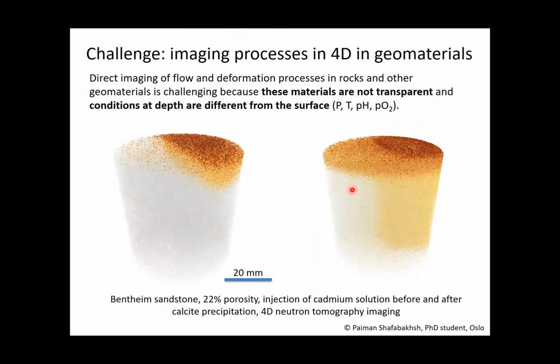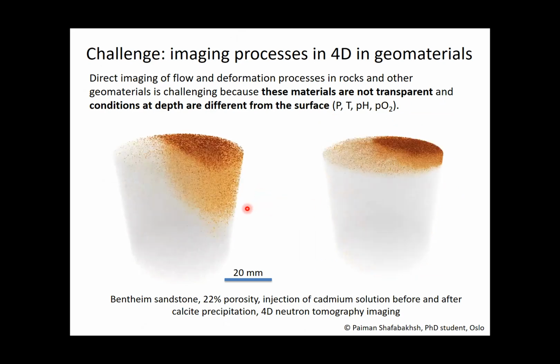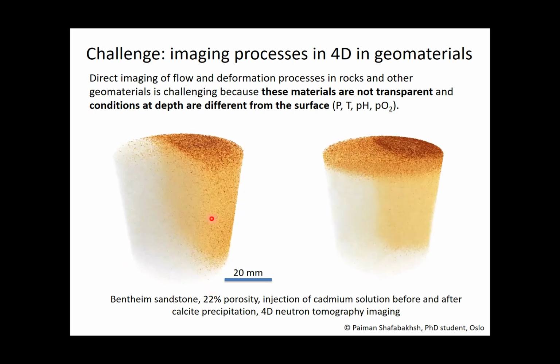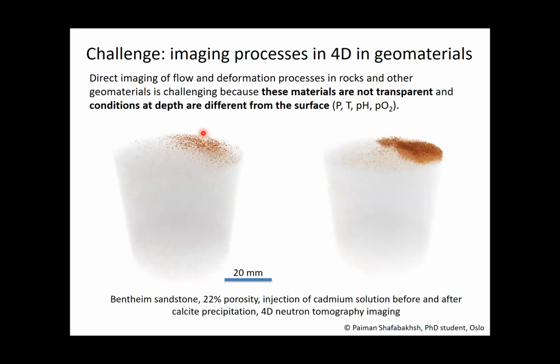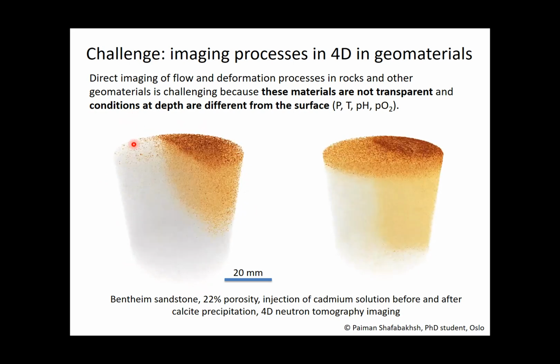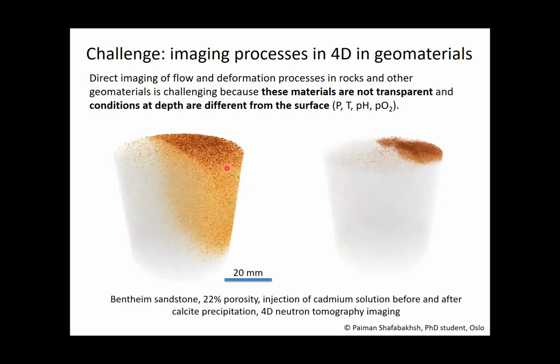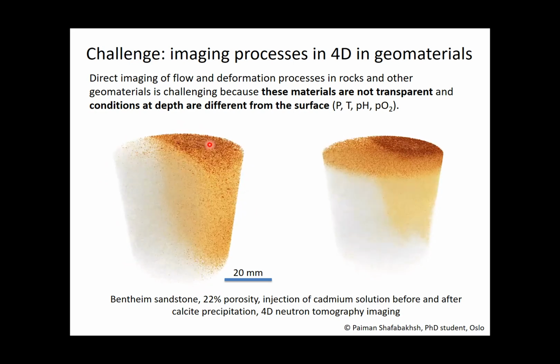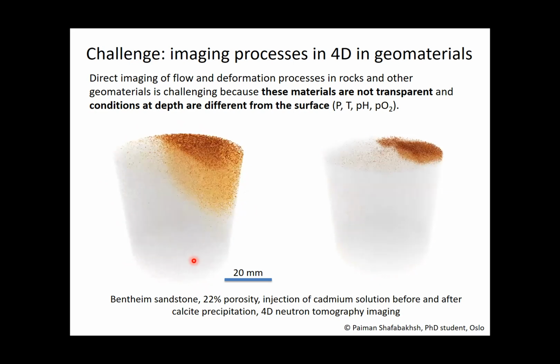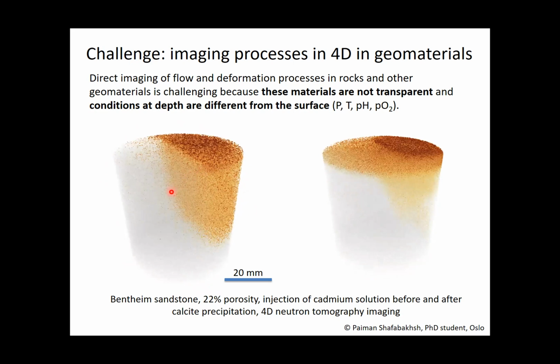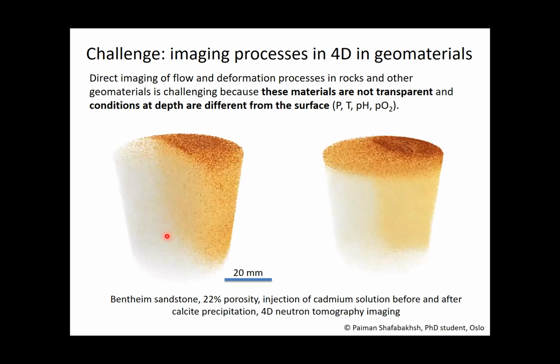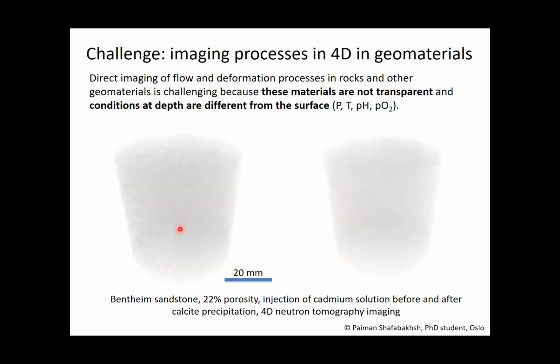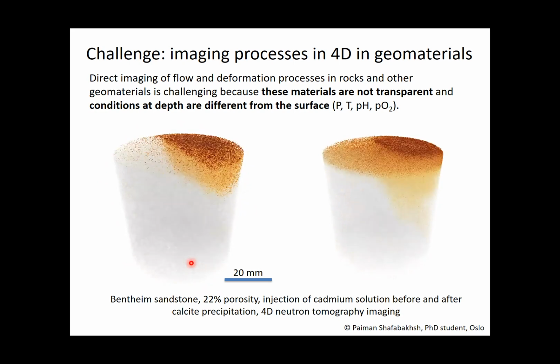So that's the same core here. It's the same experiment. It's a core of a Bentheimer sandstone, around 20% porosity, where on the top, on the right side, the fluid that contains cadmium is injected, and on the left side, there is just water. And what we see is that the cadmium-rich fluid and the water circulate downwards in the rock sample, and they will start to mix. And so there is a dispersion front that propagates also at the interface between the two.